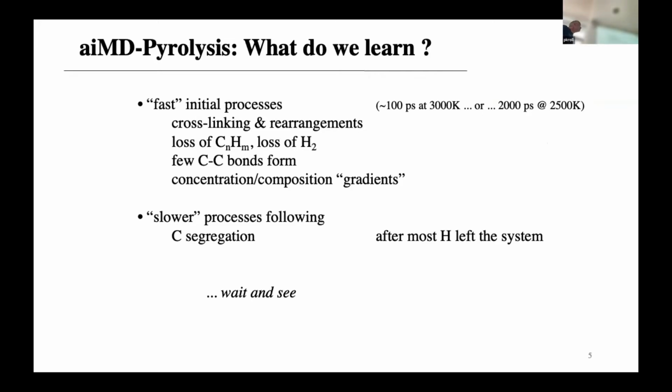This was one of the final slides after I showed you a couple of things. The outcome was, in our polymers, when we do this simulation of reactions, but also when we do experiment, we learn there are some fast early reactions going on. For instance, you remember this from all the TGA stuff, you observe cross-linking. From whatever you learned in NMR, you learned, oh yes, randomization of your silicon environment, for example, in polysiloxanes, that you get all those mixed tetrahedra.